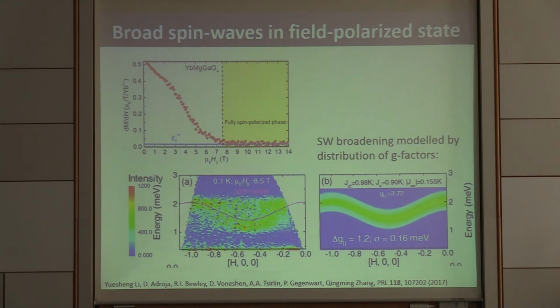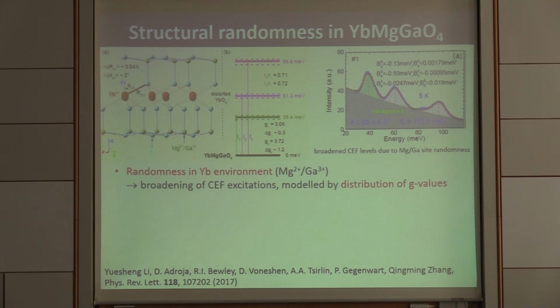There is another important ingredient in that material, and that is seen, for instance, if we look in the field polarized state, which we reach at fields above 8 Tesla. So here, instead of having sharp spin waves, we still have a broad continuum. And modeling this continuum requires, for instance, having a broad distribution of g factors. And indeed, we found that there is a structural randomness in the system, which is very important.